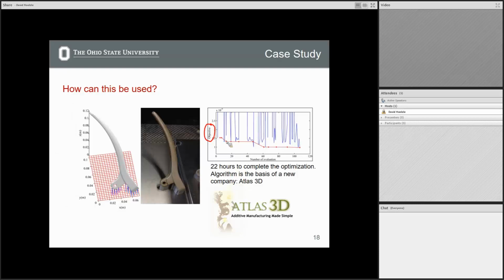Most of the orientations it chooses have really poor performance, but every so often it finds a really good orientation. And that's these blue ones. Every time we find a good orientation, that moves this red dot down farther until we get to one that's even better. And so then this objective function is eventually converging after somewhere around 100 iterations, and this took us around 22 hours to do on actually just a desktop computer, nothing too fancy.